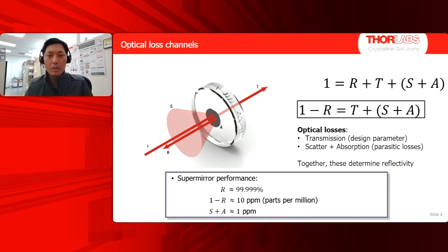And it's sometimes more convenient to talk about 1 minus R because rather than listing 5 nines, for instance, of reflectivity, 99.999%, you can just say 10 ppm as 1 minus R. And supermirror levels of performance are those sort of typical numbers you see there. And often you want to keep those parasitic losses at the sort of ppm level. And it turns out that in a lot of applications, the breakdown between 1 minus R and S plus A is important. And you want to keep the contribution of the parasitic losses to be a small fraction of 1 minus R.